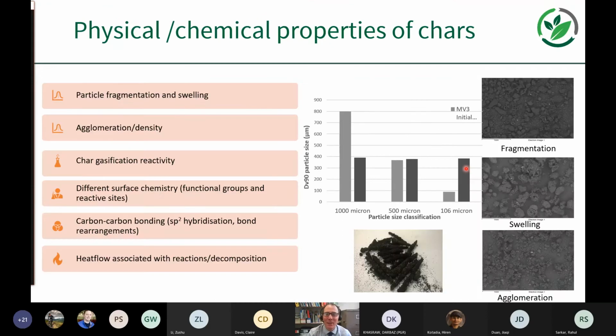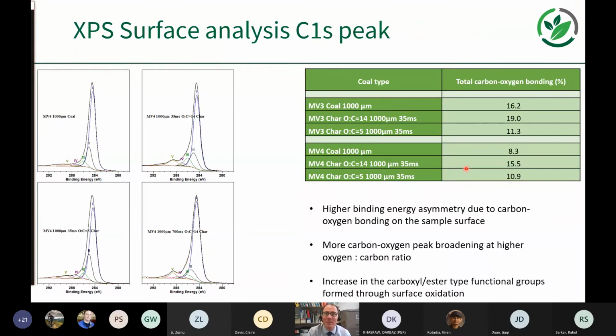So what I'm suggesting is that, when coals are injected, they behave very differently. They burn out very differently, but they also produce, because they don't completely burn out, it's likely that these chars that are formed then find their way into the blast furnace, and they exhibit different effects like fragmentation, swelling, and agglomeration. All things which are also very applicable to other particulate iron-making processes like Finex, for example, or Hisarna.